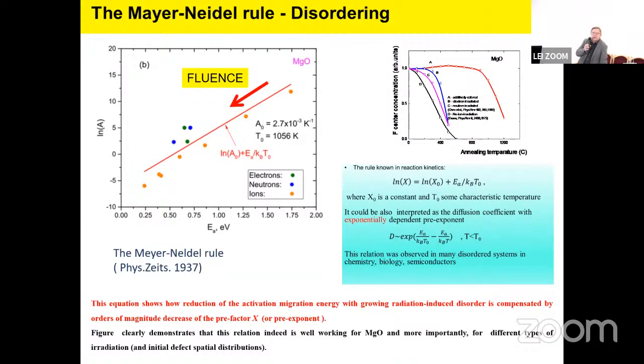But looking carefully in literature, we found that in many cases, especially in chemistry, biology, and in semiconductors, people observe that the activation energy is not fixed for a solid material, so the so-called Meyer-Neldel rule works well, and this is just the activation of the model. We know, let's say from Raman spectroscopy data, that there is degradation of the Raman peak after neutron radiation. So there is clean disordering of the material after high DPA radiation.